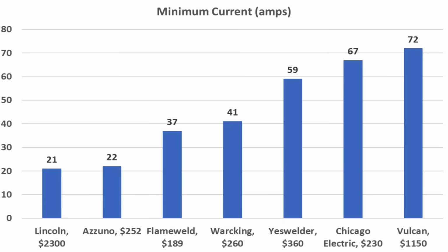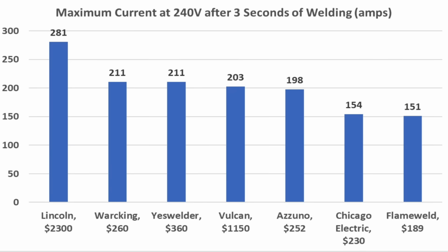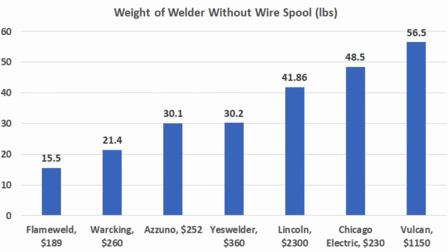Later in the video, we'll test the welders out on some very thin 20 gauge sheet metal. On the highest setting, the Lincoln makes the most current at 281 amps after 3 seconds of welding. The Warcking and the Yeswelder tied for second at 211, and Vulcan 203 amps. And tool weight can sometimes be a factor, and the Flameweld is the lightest at 15.5 pounds without the welding wire installed.